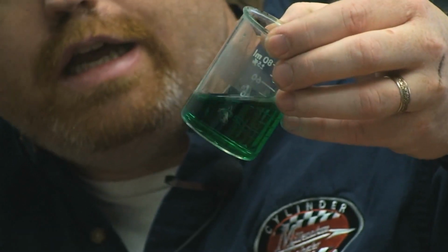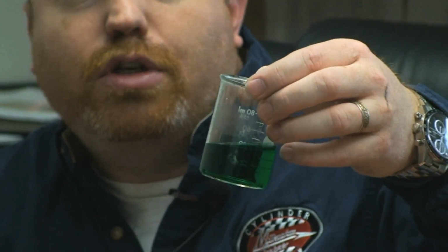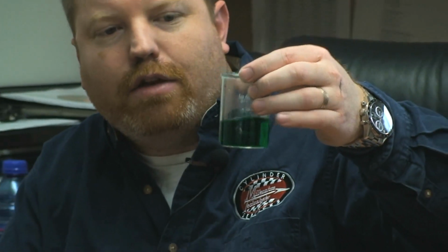The original makeup of it is a nickel plating bath and silicon carbide. When the two are mixed together, we submerge the cylinder in the plating bath, run an electrical current through it, and we get the plating. So that's how it's done, but I'll show you what the raw materials look like. This is the nickel solution, just pure nickel plating bath. There's no silicon carbide mixed into it, so that's what that looks like.